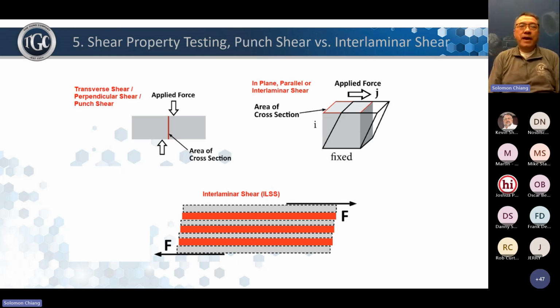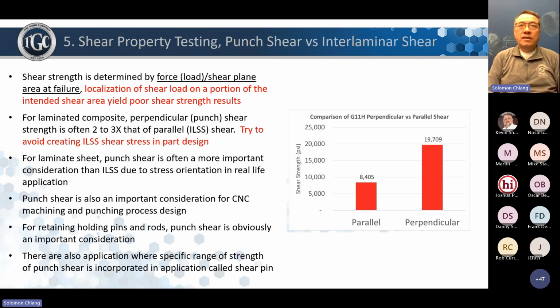ILSS, or in-plane or parallel shear or interlaminar shear, is different from punch shear because it is in the same direction as the lamination. Essentially, it is the force that's holding thermoset laminate layers together. And it is important, as I have a good example later on. The one thing I want you to remember is that the ILSS is usually 2 to 3x weaker than the punch shear strength for thermoset laminate. And that is a very important consideration for product design. If possible, we try to avoid having our components under ILSS because in a way, that's the weakest part of the thermoset laminate.